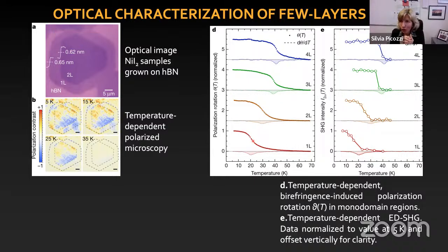What is important for our purposes is that they did a symmetry analysis on their measurement. And they can tell us that second harmonic generation shows that the inversion symmetry is broken, which means I need to have a magnetic ordering which breaks inversion symmetry. And also the symmetry analysis for the second harmonic generation and linear dichroism told us that you have a C2 symmetry. So usually you have a threefold symmetry, a triangular lattice. But here, you reduce it and you have a C2. So this is well compatible with the spin helix.